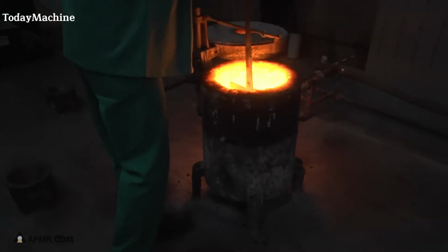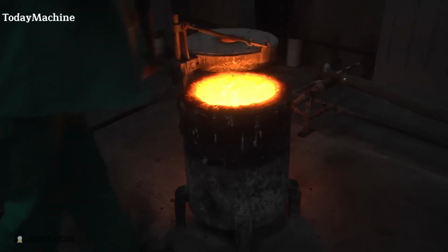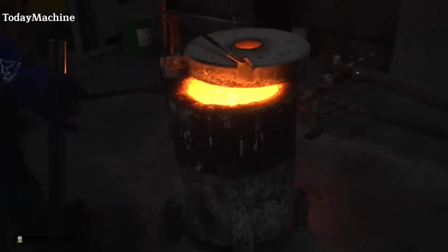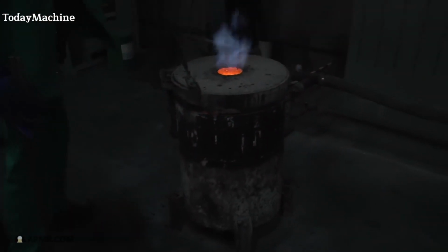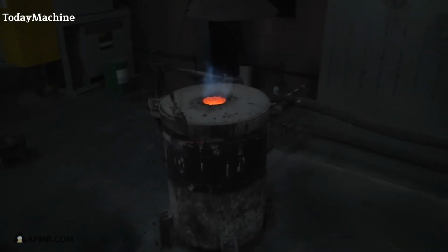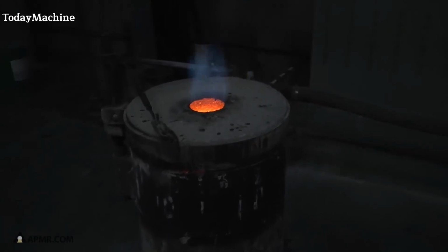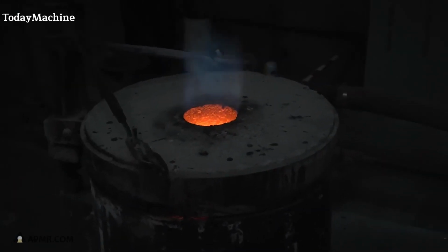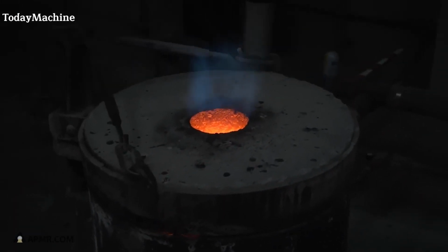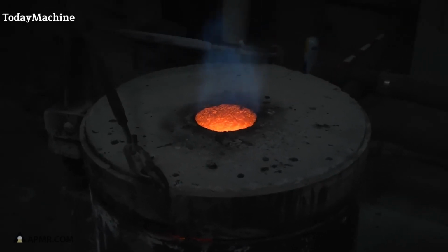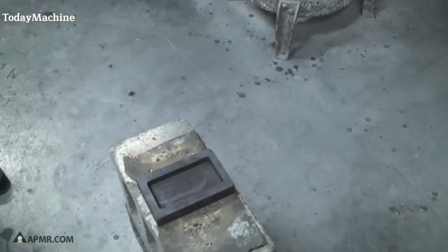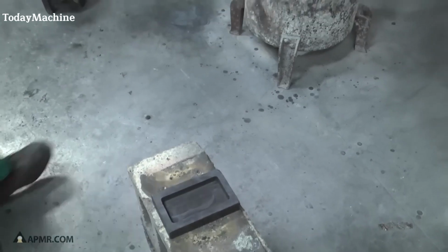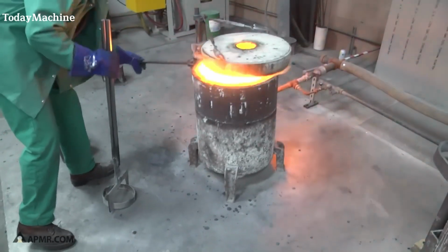The furnace operates at temperatures ranging between 1800 and 2000 degrees Fahrenheit. This intense heat is necessary to completely melt the gold. The process typically takes about 15 minutes, depending on the amount of gold sponge being melted. During this time, the gold transforms from its solid, spongy form into a molten state, ready for pouring. Once the gold is fully molten, the crucible is carefully removed from the furnace using tongs due to its extreme heat.